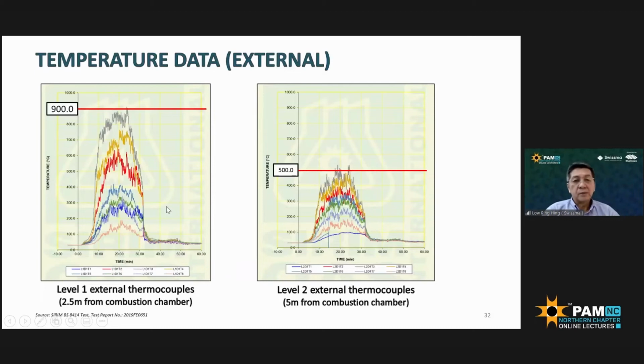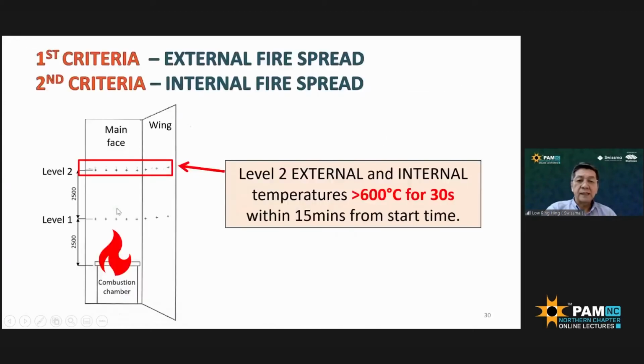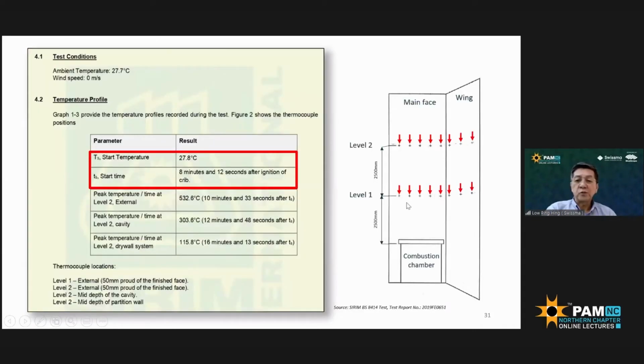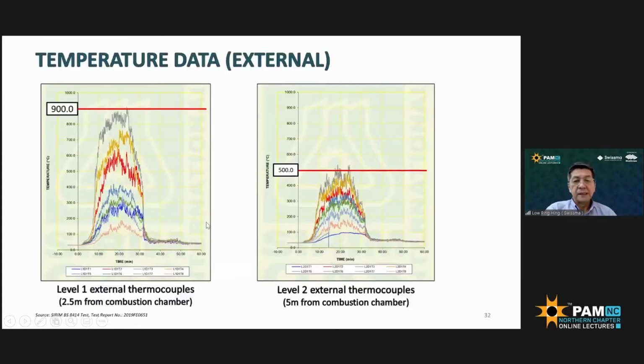So this is a thermograph. The temperatures are recorded in the test lab. Here is the level one external thermocouple, which is 2.5 meters above the combustion chamber. The highest temperature recorded hits about 900 degrees Celsius at level one. Whereas level two, where the temperature is the one that triggers the criteria, is recorded at 532, as I read out just now.